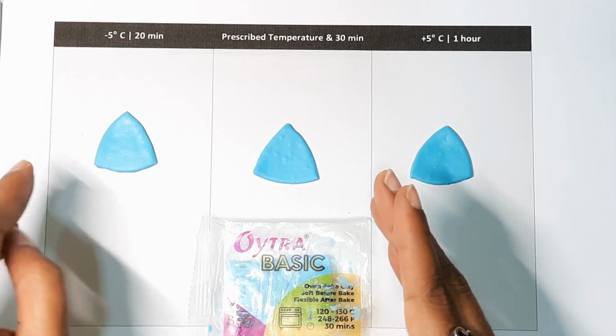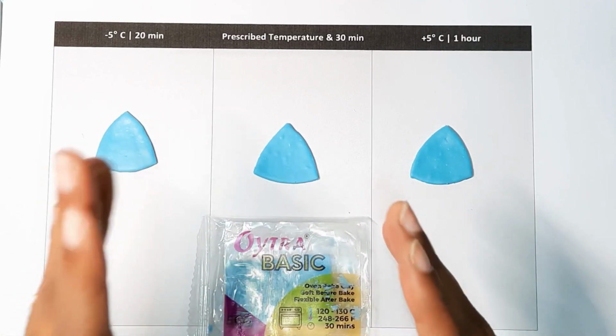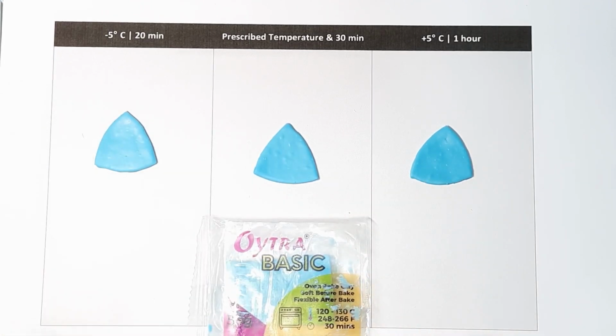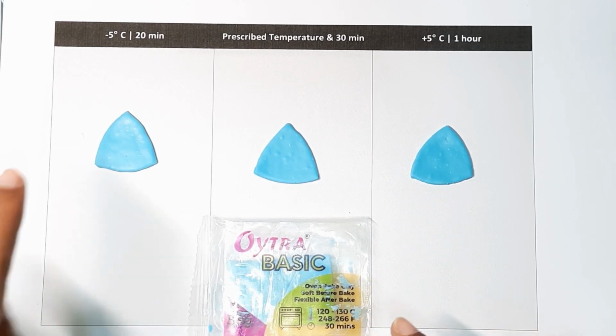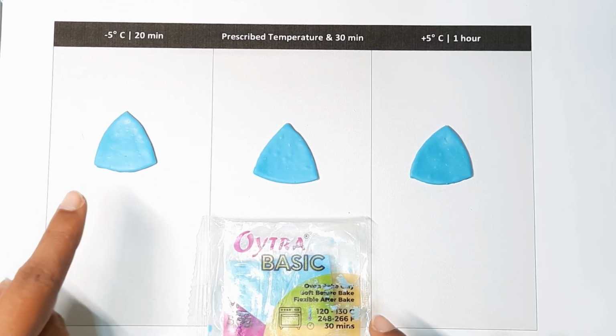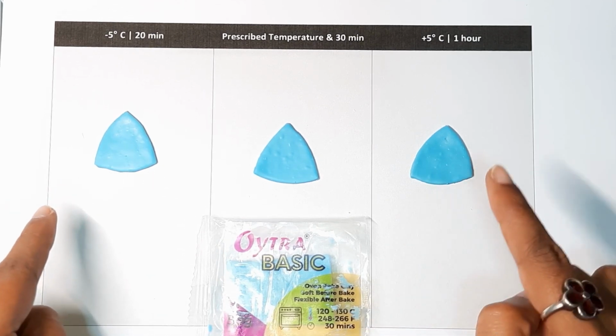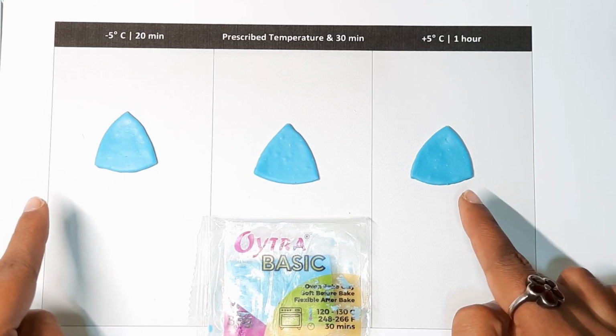Prescribed temperature, minus 5 degrees, plus 5 degrees, and a variation of 30 minutes, 20 minutes, and 1 hour. The prescribed temperature for this variant is 120 to 130 degrees centigrade. This is similar to the classic series, and the prescribed bake time is 30 minutes. So I have stuck to 130 degrees centigrade in this, taking the higher limit, and also stuck to the prescribed bake time of 30 minutes. The other variant is baked at 125, and the third variant is baked at 135